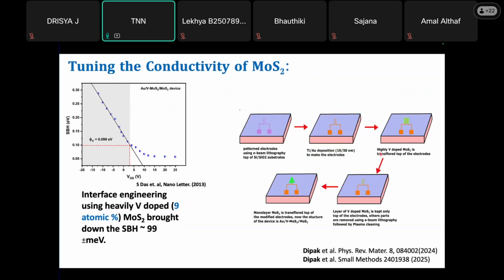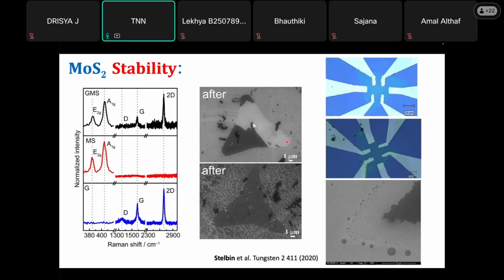And we showed that we can do very nice patterning with these two semiconductors. So you have gold with a degenerately doped MoS2 with a semiconductor MoS2. This junction will work as a low-resistance contact junction for MoS2 transistors, which can perform as good as a titanium-based contact. But titanium contact will not be useful because titanium's long-term stability will be a question. So this is one aspect of interface engineering. I hope I could convey to you how important interface engineering is.